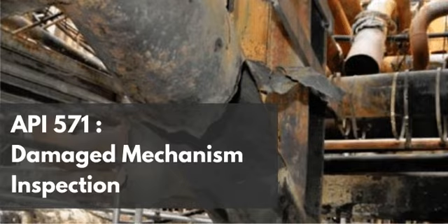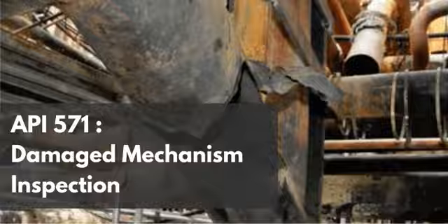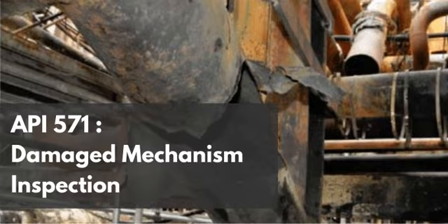Okay, then the rich amine moves to the regenerator and stripper section. And this is arguably the most severe environment. The regenerator uses high heat to boil the rich amine, forcing it to release the absorbed H2S and CO2. So you have the worst possible combination here. You really do. You have high temperatures, which increase the kinetic energy of the corrosion reactions. You have dynamic phase transitions as the gas flashes off, which strips the protective FeS scale. And the bulk fluid is aggressively returning to its highly reactive lean state. It's a perfect storm.